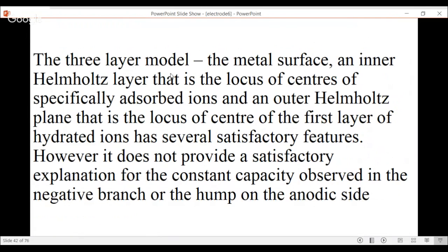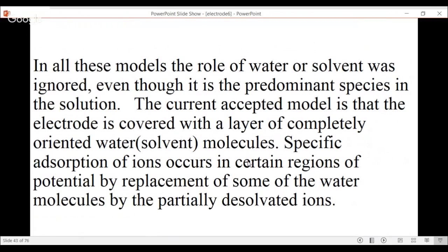The three-layer model has the metal surface, the inner Helmholtz layer, that is the locus of the centers of the specifically adsorbed ions, and another outer Helmholtz plane, that is the locus of the centers of the first layer of the hydrated ions. It has several satisfactory features. However, it does not provide a satisfactory explanation for the constant capacity observed in the negative branch or the hump on the anodic side. So therefore, all these models are only approximate. They cannot quantitatively give rise to the behavior of the electrode-electrolyte interface.